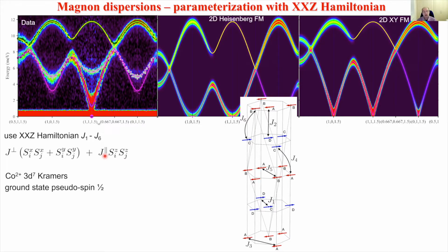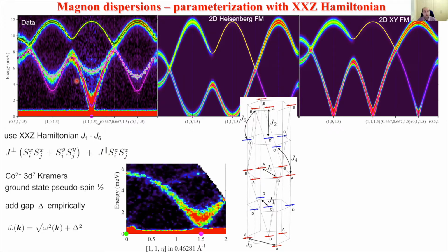And then the exercise would be to add to J1, which is the nearest neighbor coupling, also other bonds, J2 for interlayer and various other interlayer couplings and second neighbor in planes and so on, until we get a good explanation of the measured dispersion relations. Now, one feature that's not explained by this model is the gap that we clearly see above the Bragg peak.